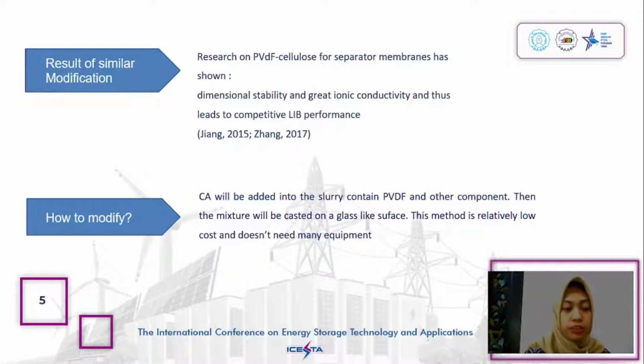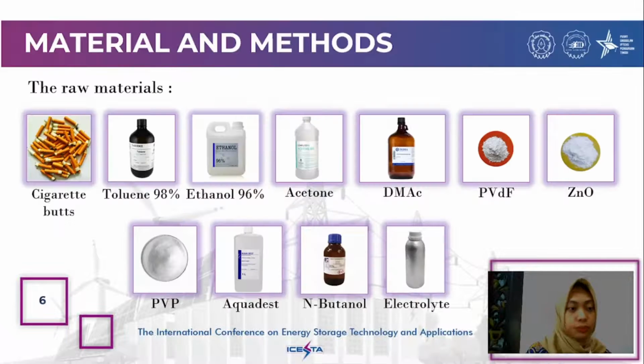So how to modify this separator? We will add cellulose acetate into the slurry containing PVDF and other components, and then the mixture will be casted on a glass-like surface. This method is relatively low cost and doesn't need much equipment. So these are the materials we use: cigarette butts, toluene, ethanol, acetone, DMAC, PVDF, ZnO, PVP, aquades, normal butanol, and electrolyte.